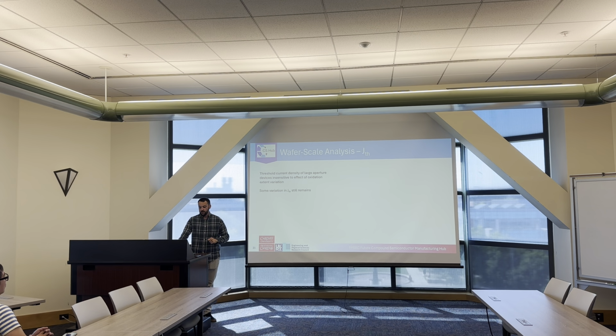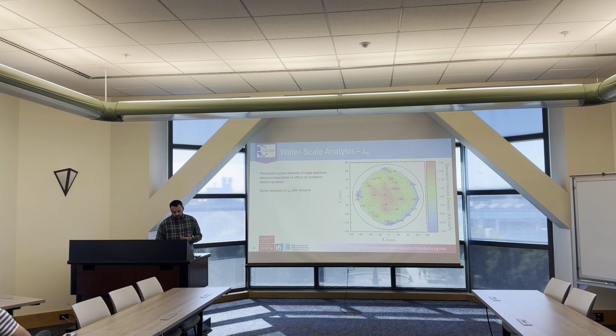I'm not going to go through every single parameter of the map here, but I'm going to show the threshold current density variation. To get rid of that oxidation effect from the device, we can look at the threshold current density of large aperture devices, where any variations in the oxide aperture are less important. And there's still some variation in the threshold current density that remains. So it's higher in the center, lower towards the edge.